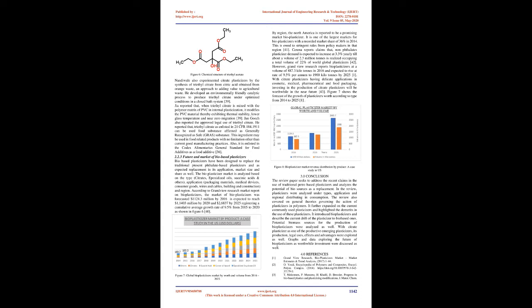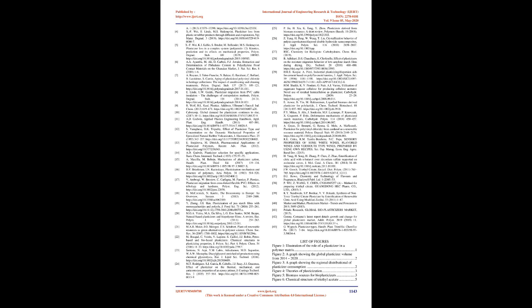Cardanol is a particular vegetable oil that is obtained as a byproduct from the distillation of cashew nut shell. Cardanol was initially analyzed and used for plasticization of soft PVC. However, the results showed partial miscibility with PVC. On the contrary, the epoxidation of the esterified compound showed good miscibility with PVC. The esterified cardanol was adjudged to be suitable as a secondary plasticizer, whilst the epoxidized esterified cardanol could be used as primary plasticizer. Table 2 shows the comparison of common bioplasticizers.